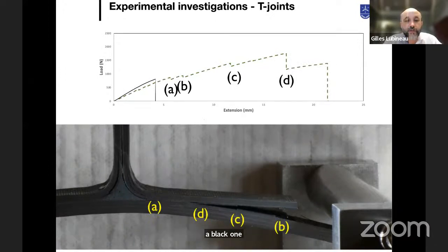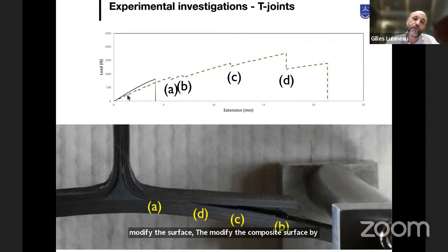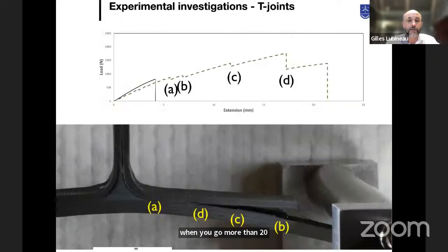And this is exactly what you get when you start to modify the composite surface by using this laser surface treatment. And you see that you have a huge improvement in the ductility of the T-joint when you go more than 20 millimeters. So this is the first strategy that I wanted to present to you.